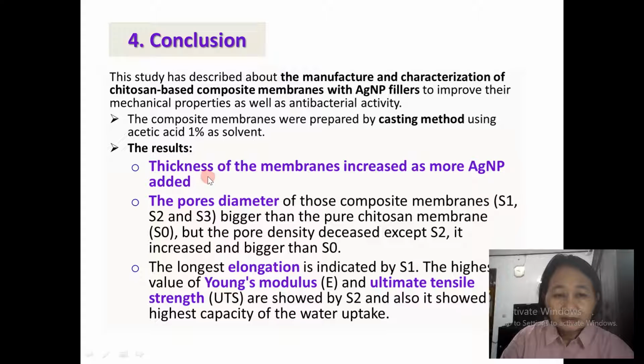The results: thickness of the membranes increased as more silver nanoparticles were added. The pore diameter of the composite membranes S1, S2, S3 was bigger than the pure chitosan membrane S0, but the pore density decreased, except S2, which increased and was bigger than S0. The longest elongation is indicated by S1. The highest Young modulus and ultimate tensile strength are shown by S2. It also shows the highest capacity of water uptake.